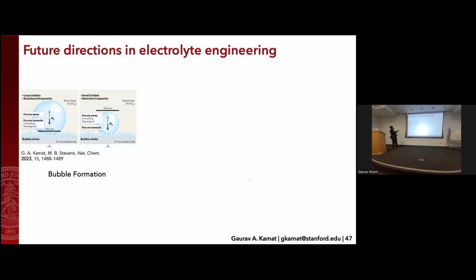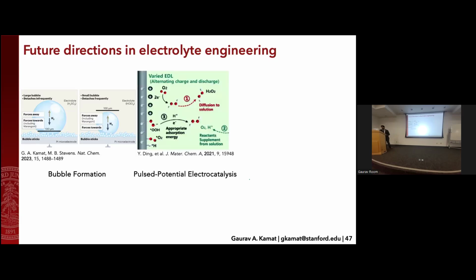But there's a lot of evidence that shows that using an electrolyte such as sulfuric acid changes the forces on a bubble that is on your electrode and changes at what size it wants to detach from your surface, just based on a simple force balance. Now, this is important because you want to free up as much of your surface as possible. So you want bubbles to take up less and less of your surface in order to get the most out of your catalyst. And electrolytes may be one way to get there.